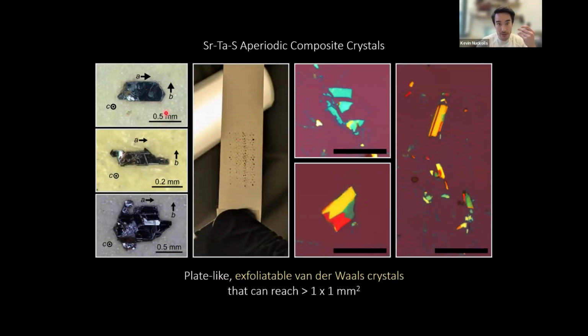Here are some aperiodic composite crystals that I discovered in the strontium tantalum sulfur ternary phase diagram. You can see they come in a wide variety of macroscopic crystal facets, depending on how you grow them, but they're all plate-like, and they're all exfoliatable van der Waals crystals. So here's me exfoliating using Scotch tape. You can see the crystals copy nicely onto regular Scotch tape, and we can deposit them onto silicon dioxide. These crystals over here with AFM we saw were about 10 nanometers thick. I think you could probably exfoliate them thinner. I didn't really try. I hope that the community tries further, but they clearly exfoliate like graphite or TMDs.